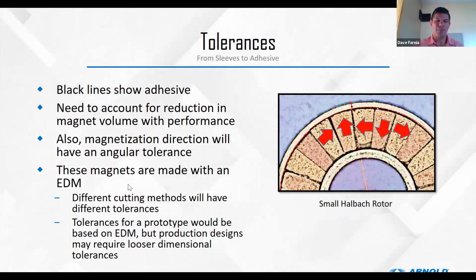So once we make those magnets, then we have to bond them into the rotor. So this little rotor cross section here, the black lines show our adhesive. On very large rotors, those bond lines, they're not that big compared to the magnet. On something that's an extremely small rotor like this, the bond lines will start to affect performance. So we really need to account for the magnet volume as a function of, well, tolerances and then bond lines.